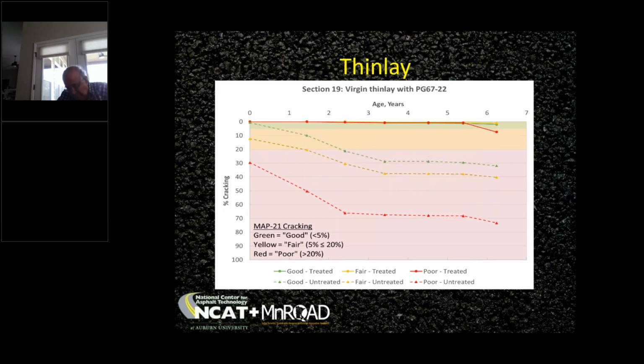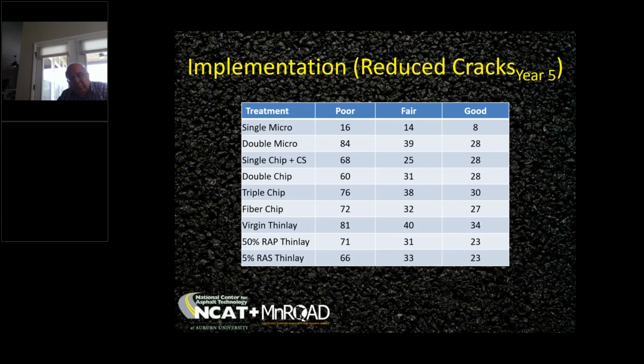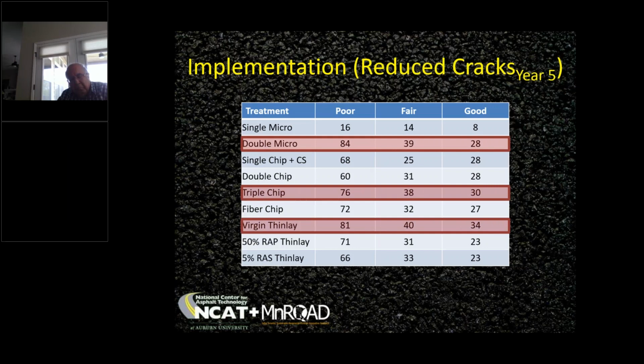Compare that to the thin lay test section on Lee Road 159, and again, we've got a high traffic version in the south, and then low traffic and high traffic up north in Minnesota, where we have all the same treatments. What you see with the thin lay is significant benefit, regardless of whether the pavement was in good, fair, or poor condition. And you can take that type of cracking reduction information and, for example, go into year 5 and look at the gap between the solid and the dashed lines for pavements in poor, fair, and good condition.